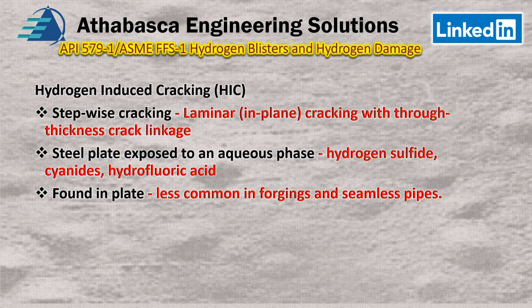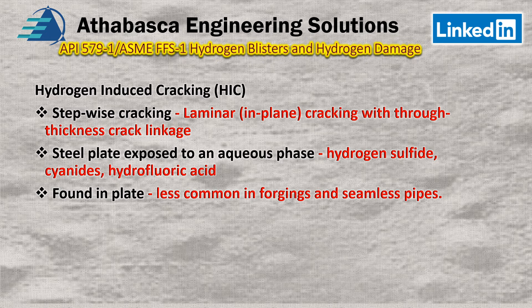The most common occurrence is in plates, but it's less common in forgings and seamless pipes — and this has to do with the grain structure. I've always thought that with plate, they use manganese to tie up the sulfides in the process, so you get a lot of manganese sulfides in the steel grains. I've always suspected that this may be where hydrogen can accumulate, which is why it's most common in plate. In forgings, the grain structure is linear, or in seamless pipes the manufacturing process is different — and that's also why those are considered higher-strength materials.